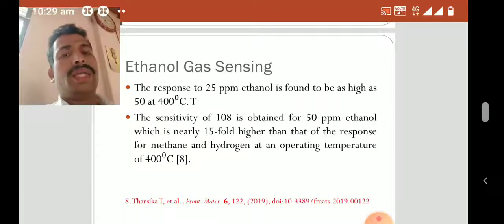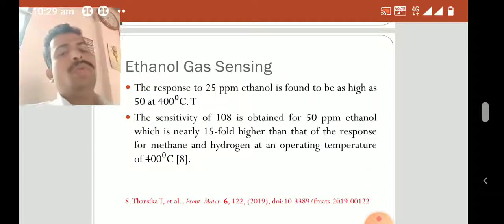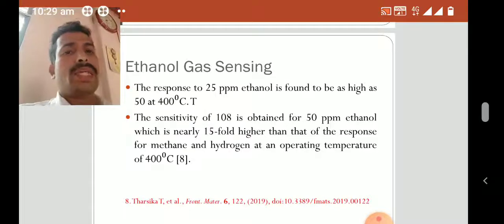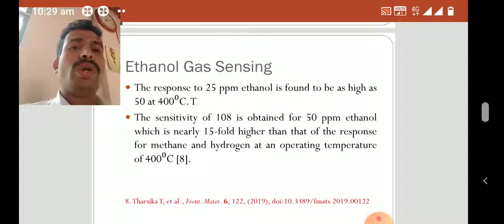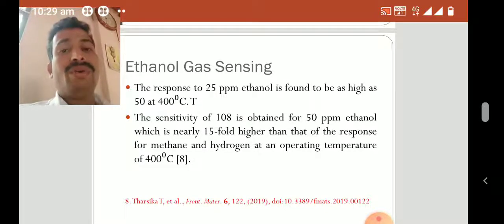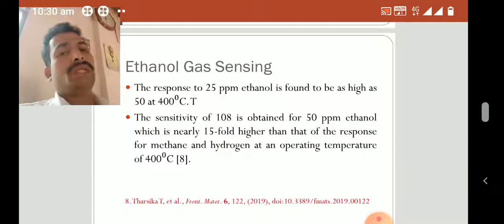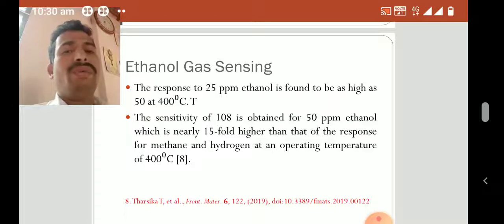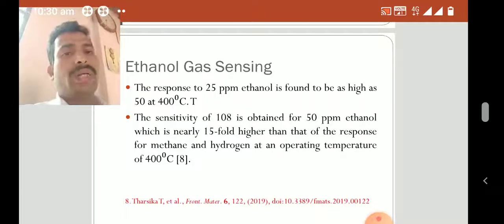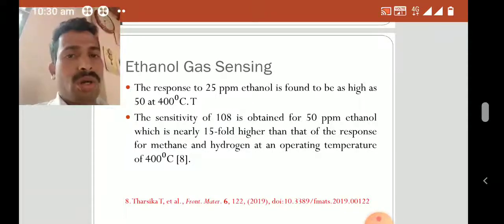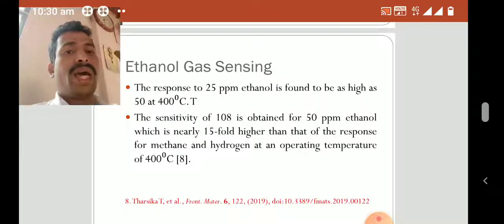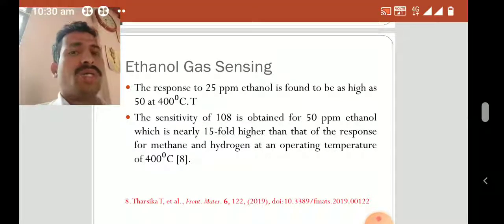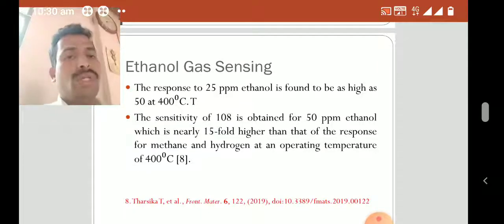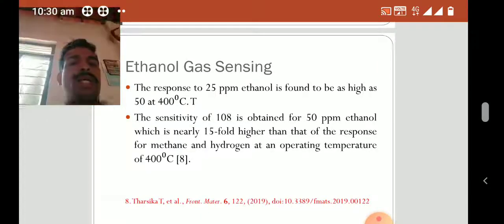Another study by Tharsika T and her group is on ethanol gas sensing. Here the response to 25 ppm ethanol is found to be as high as 50 at 400 degrees Celsius temperature. The sensitivity of 108 is obtained for 50 ppm ethanol, which is nearly 15-fold higher than the response for methane and hydrogen at an operating temperature of 400 degrees Celsius.